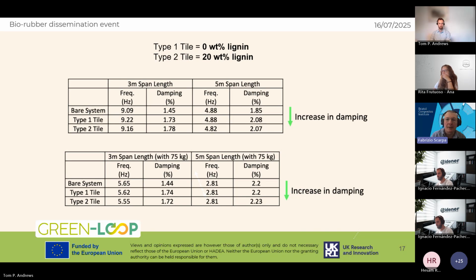Something similar can also be seen when we put a static mass of 75 kilograms representing a person on top of the other two, rigid and flexible, platforms. In this case, you can see that there is an increase in damping, especially on the more flexible configuration. However, if you look at the specific figures, we are talking about some sort of marginal increases. And what is noticeable is that, especially when we have the presence of the mass, we always have a decrease of the resonant frequency of the base platform as soon as we put the mass and the panels. Next, please.